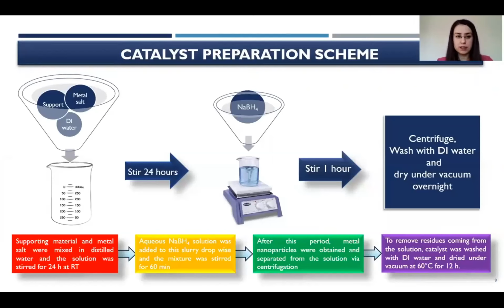For the iridium ceria synthesis, metal salts and supporting material were mixed in distilled water for 24 hours at room temperature. After the 24 hours, aqueous sodium borohydride solution was added to the slurry dropwise, and the mixture was stirred for 60 minutes to obtain dispersed iridium nanoparticles on the ceria surface. After this period, metal nanoparticles were obtained and separated from the solution via ultracentrifugation. To remove residues coming from the solution, the catalyst was washed with distilled water and dried under vacuum at 60 degrees for 12 hours.